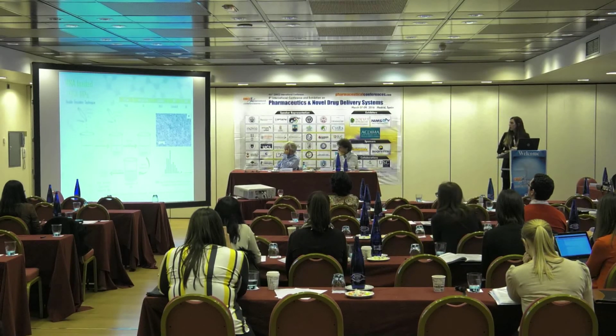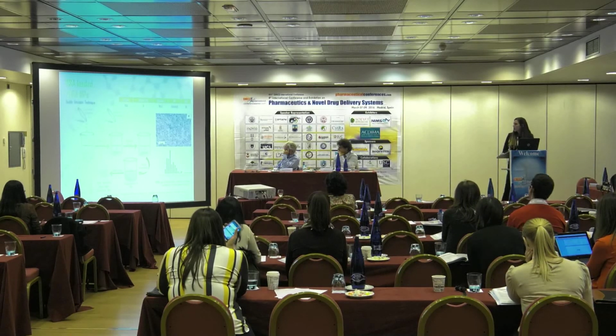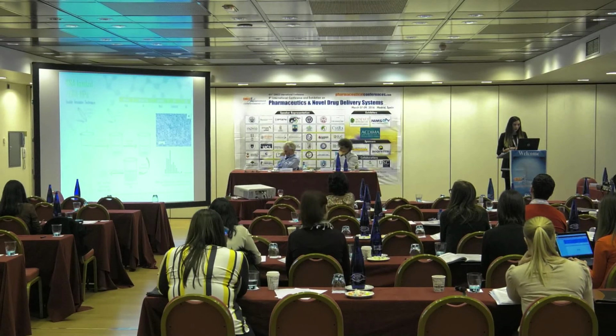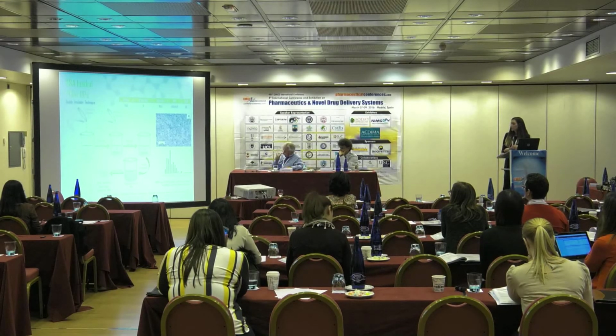In that case, getting a copolymer between polylactic acid and polyethylene glycol is very useful because of the functionalization of the surface. Well, the first system that I want to talk about is a previous work that we have made in the group here in Spain, in which we could get bovine serum albumin loaded PLGA nanoparticles. This is a pretty challenging thing because of the work that you should keep in mind when you are talking about hydrophilic drugs. It's always a little bit more challenging than hydrophobic drugs, and in this case we used a laboratory method, the double emulsion technique. As you can see, this method requires you to make 2 emulsions in order to get an aqueous suspension of nanoparticles.